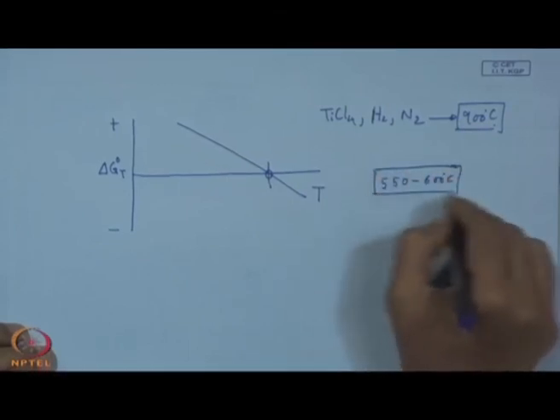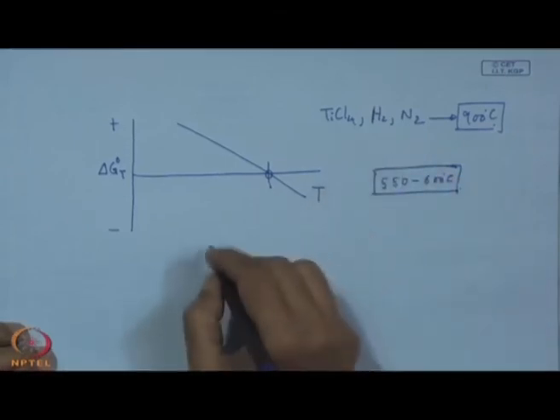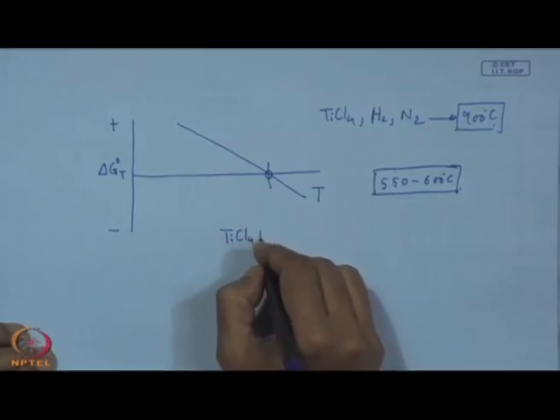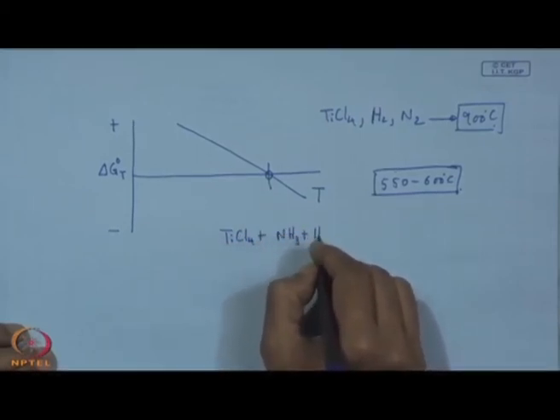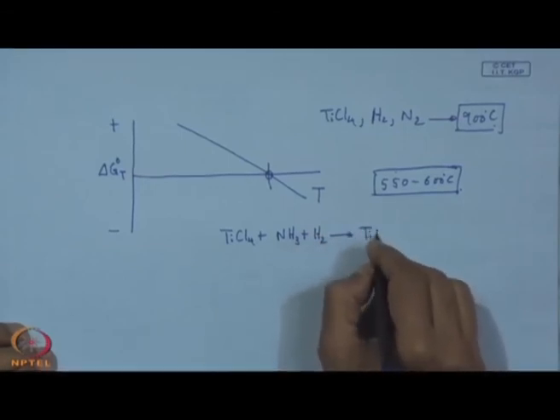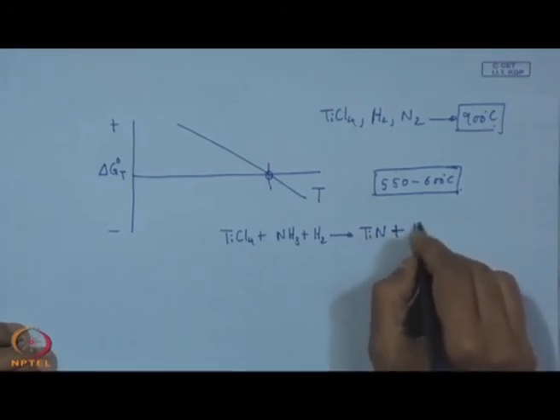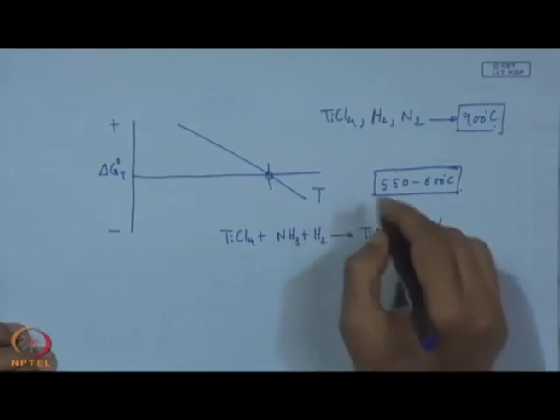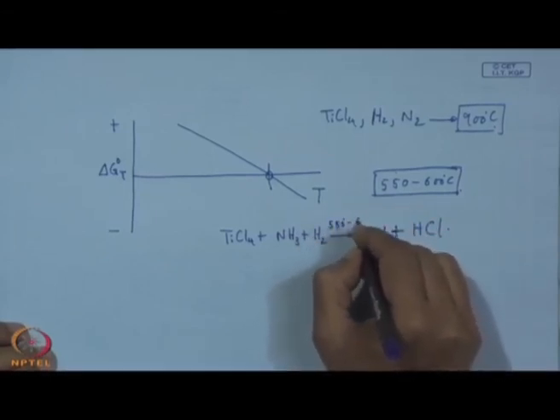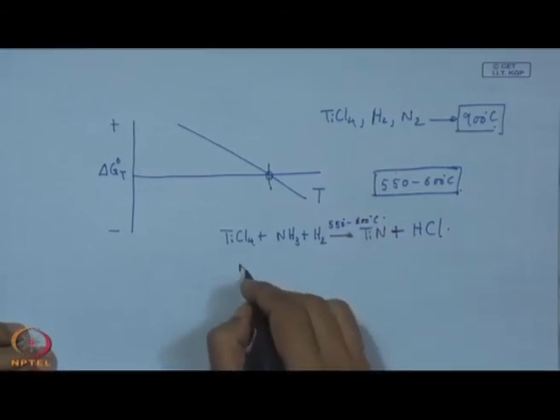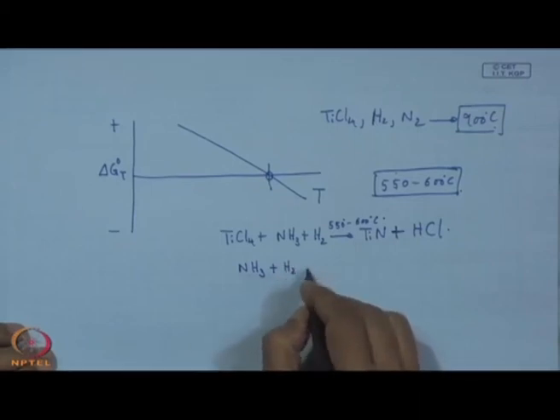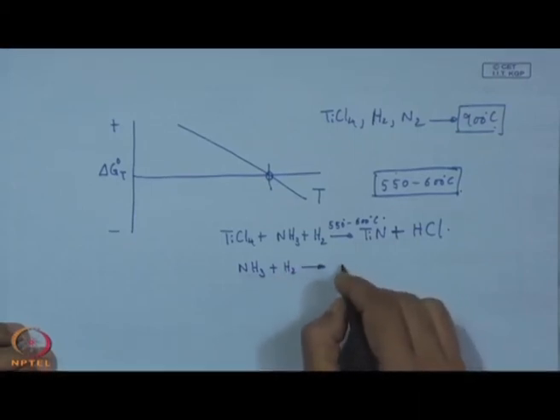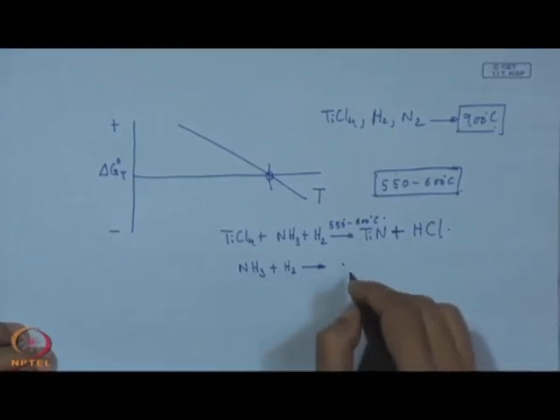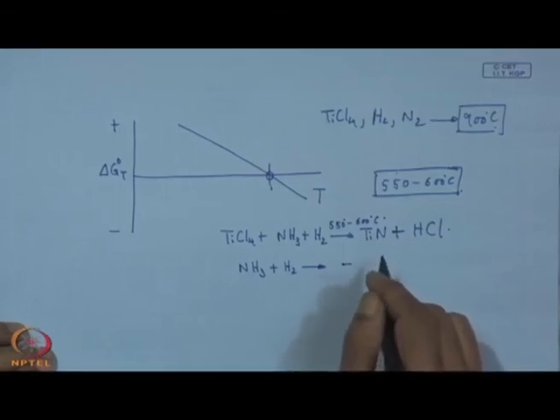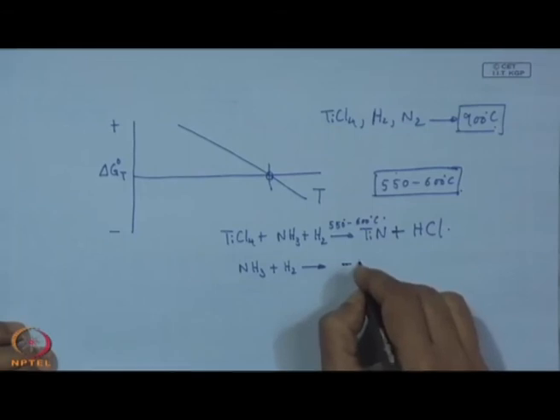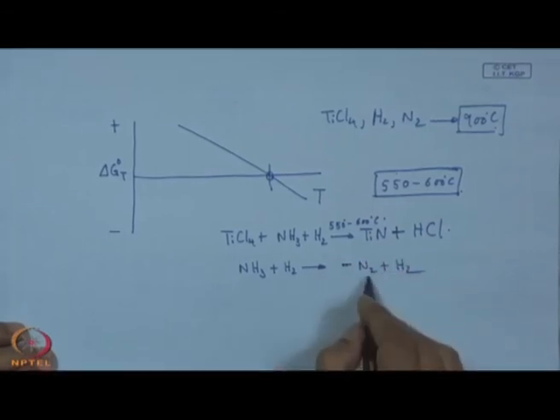then some attempt can also be made with, instead of nitrogen, using ammonia, and in this case it is something like NH3 plus H2 that gives TiN plus HCl, and this can happen at this temperature of 500 to 600 degrees centigrade. However, here we have this breakup. NH3 gives actually N2 plus H2. So, that will be split here.